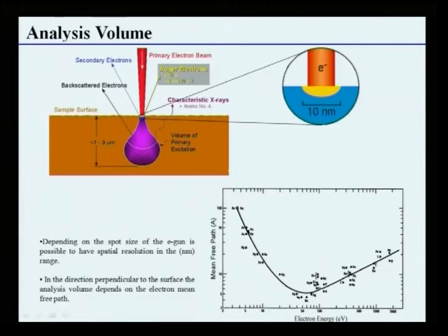As you know, when a certain energy source falls on the sample material, it interacts with the material and creates a volume of interaction, or interaction volume rather. The X-rays come out from a large volume; these are characteristic X-rays, as you see here, for atomic number higher than 4. Backscattered electrons also come out, and secondary electrons come out from a much smaller level. Auger electrons come out only from 40 to 50 Angstrom. This is the depth from which they can come out, very small.